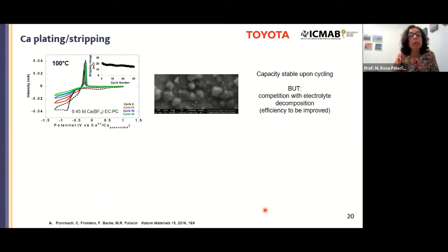Just by increasing the temperature to 100 degrees C, we were able to see calcium plating and stripping. This is a conventional salt, and conventional solvents like those used for the lithium-ion technology. Here you see some cyclic voltammetry experiments where you can see that the plating and stripping takes place. This is an image of the deposits, but of course 100 degrees C is not very practical. And again, we have a problem with the efficiency of this deposition, because there is also electrolyte decomposition, and this is enhanced by the higher temperature.